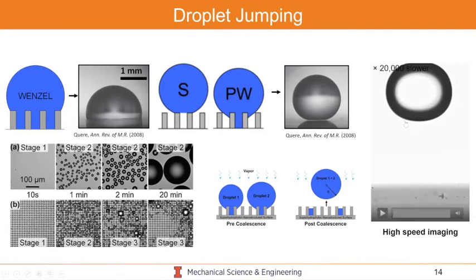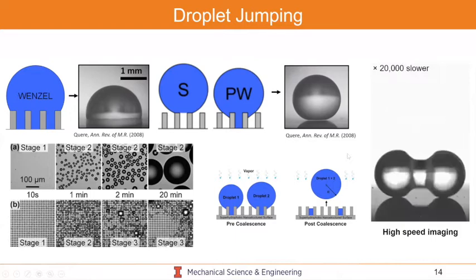Now, to have this process happen, you have to have surfaces which are superhydrophobic or highly non-wetting. So the state of the droplet residing on the surface has to have a very high contact angle and very low adhesion. That's very important because if it has a high adhesion, the droplets will not depart. They'll stick to the surface. So why is this process very useful? Well, it turns out in many applications, it's very useful to remove your liquid from the surface before it could freeze or solidify or accrete onto the surface and hinder performance.